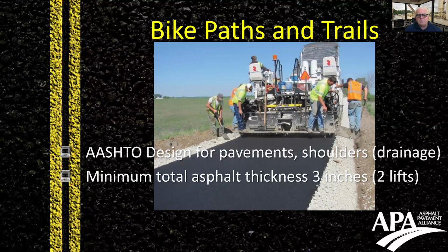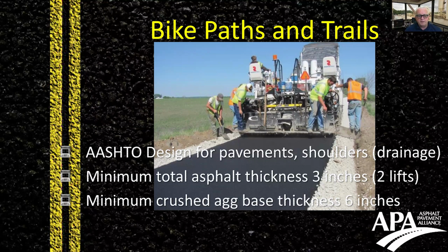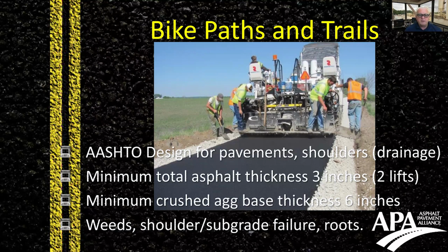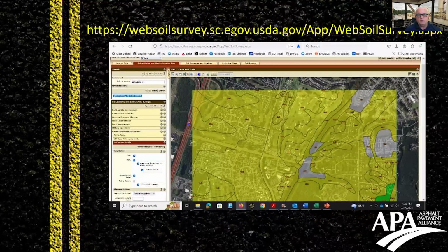You're typically looking at a minimum total asphalt thickness of 3 inches, probably 2 lifts, and a minimum crushed aggregate base thickness of maybe 6 inches. And then the big concern that you have there is weeds and roots, and then shoulder and subgrade failures, especially out near the edge of the pavement. You have to approach this sort of like a low volume roadway, and then just make sure you do a really good job with the design and with the buildup.